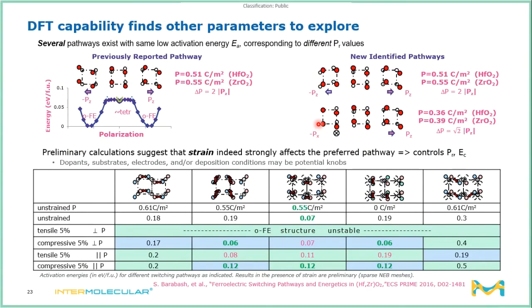This could be really important because ultimately this will have an effect on the coercive field, for example, in the sample, and that is a key parameter on the electrical polarization versus voltage plot that tells you how much voltage you need in order to switch this system from one state to another. And so again, not just our experimental lenses that we used before, but simulation lenses can really help us understand the mechanism underlying things and then go after experimental pathways that support those mechanisms in order to get us the electrical performance that we want.